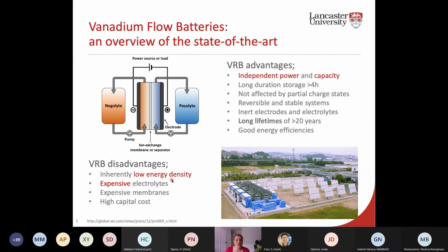So one of the main issues with a redox flow battery, and this is going to be across the board, is that you've got a solute and a solvent. And once you move to a solute and a solvent system, you're looking at low energy density intrinsically, because you've got this heavy solvent that is also part of your energy density as well. So you're limited in how much energy density you get by how much solute you can get into that solvent effectively. And that's inherently going to make this system low energy density.